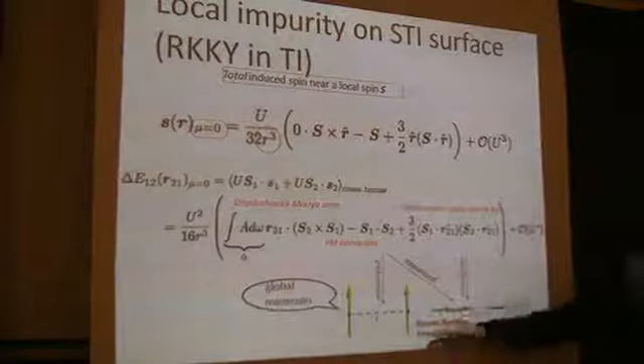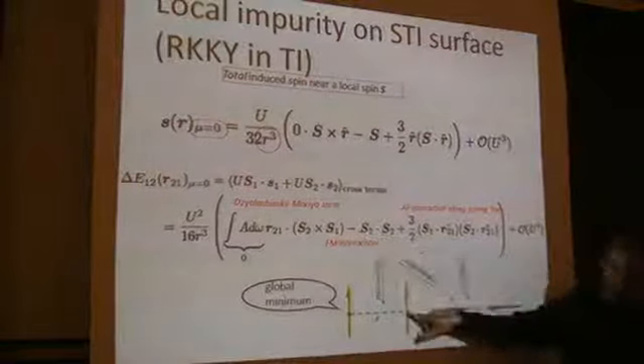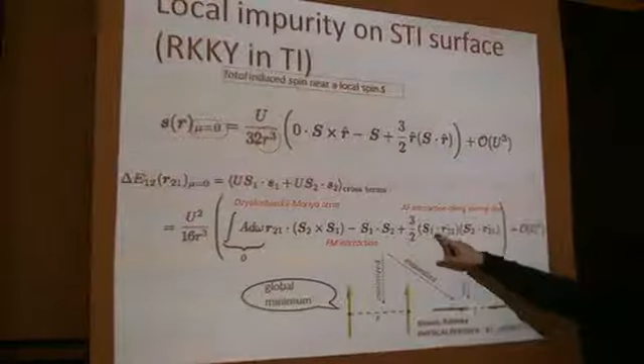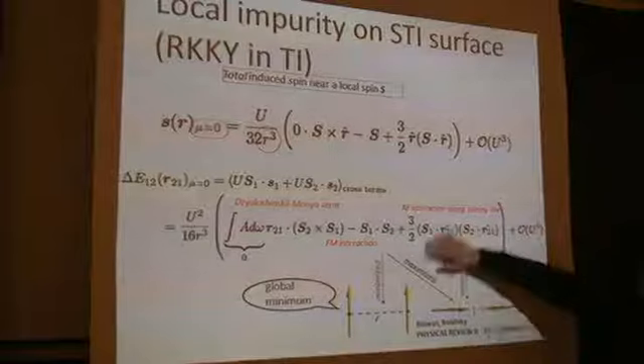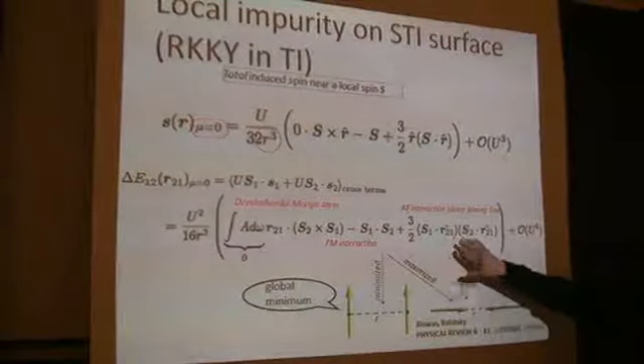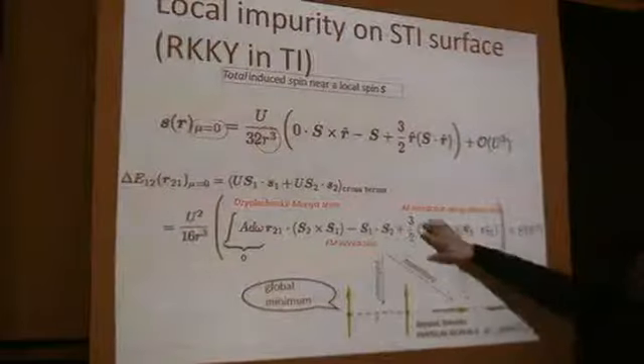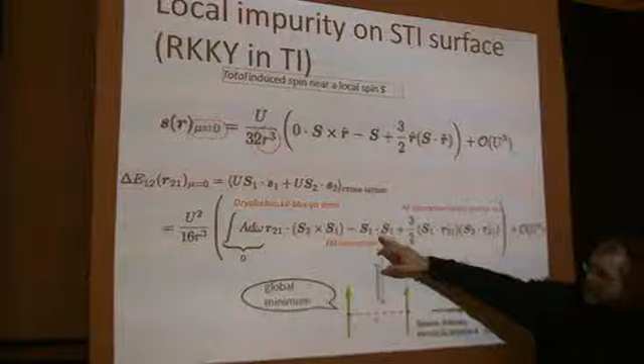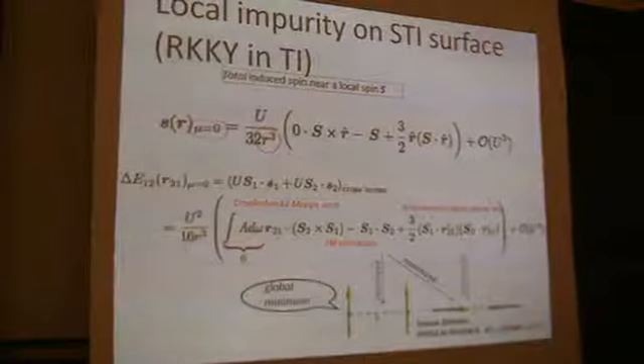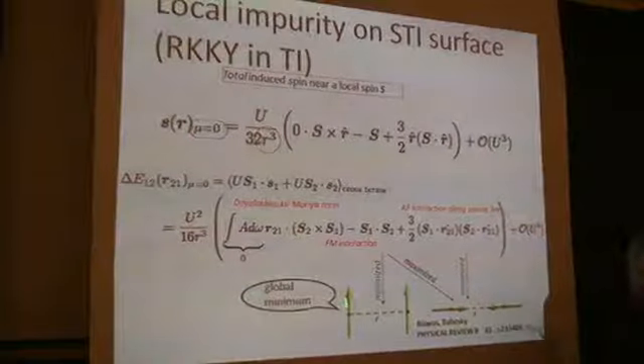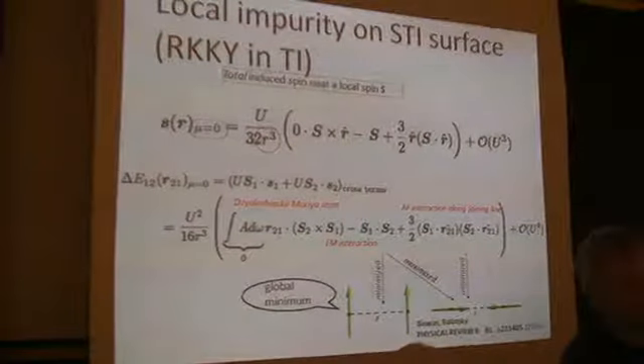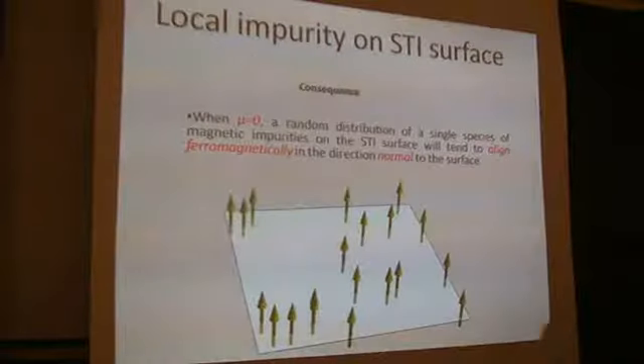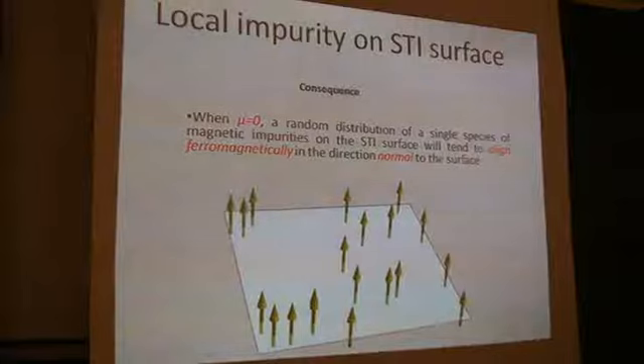So you play with the numbers and you find out that if the spins are pointing out of the plane, they take advantage of -1, and they have a 0 for this energy because S dotted into the unit vector along the 1, 2 direction is 0, so this term is 0. So there is the energy gain of -1, and if you want to maximize the dipole piece, then you will get the energy gain of 3/2, but you have to lose 1 because you have to pay the price for ferromagnetic coupling. So the answer is that the global minimum is for all the spins to point out of the plane. So they do prefer to couple ferromagnetically, and it's as if spin-orbit coupling produces an easy axis and likes to polarize all the spins out of the plane. And in this case, there is no beating, so it's not the RKKY that takes advantage of peaks and troughs in the oscillating function. It's just basically playing with the power law tails.